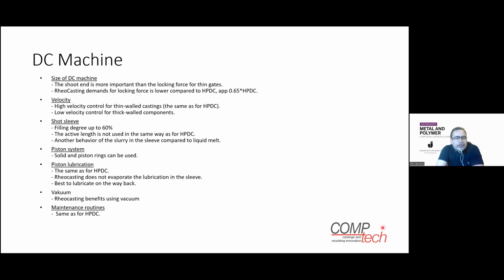Then we come to the piston lubrication. We use the same types as we use for conventional high pressure die casting, so no change here. But we have seen that when we cast these highly loaded components, the amount of lubrication that you apply is important, so we don't take the piston lubrication into the cavities. Therefore we would recommend that you use a lubrication system that lubricates on the return stroke of the piston, instead of pouring it on the piston, so to say.